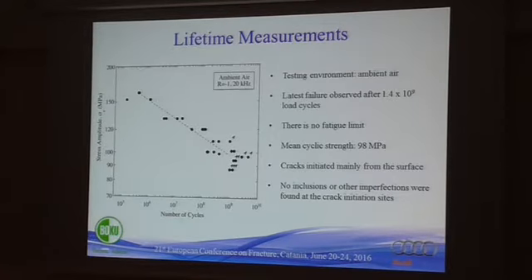So let me now present you the results of the lifetime measurements. As you can see, we still observe failure in the gigacycle regime. This means the material shows no fatigue limit. We have a single slope curve with no transition in failure mode. Cracks initiated mainly from the surface, with some rare exceptions where the crack initiated from the subsurface. And no inclusions or other imperfections were found at the crack initiation sites.